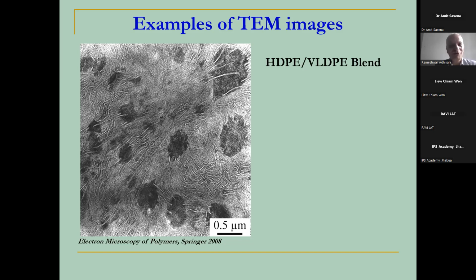I'm sure you have been already thinking, okay, this should be polyethylene and this should be very low density polyethylene. Without giving you any surprise, I will tell you about these areas, the darker areas. Because these are polyethylenes, made of only carbon and hydrogen, there is no possibility of imaging their segregation, their structures, without staining. So this material was stained with ruthenium tetroxide.